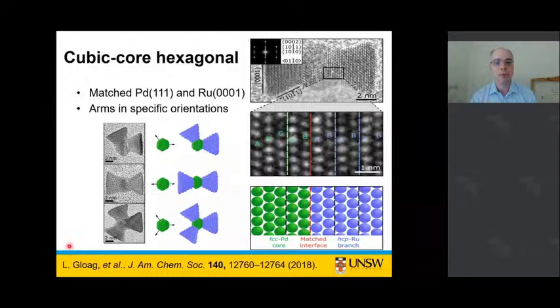So this is another paper from Lucy. In this case, we have palladium as our seed. We have very good matching of the spacing of the palladium atoms with our ruthenium atoms. And so we do get this epitaxial growth. And then we get these very precise angles. So 180 degrees, 120 degrees, 109 degrees when we're growing off these specific facets.